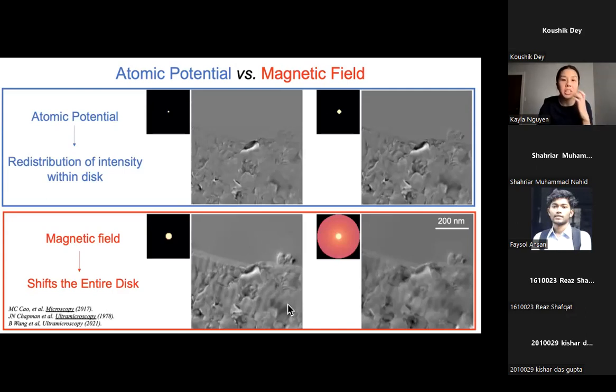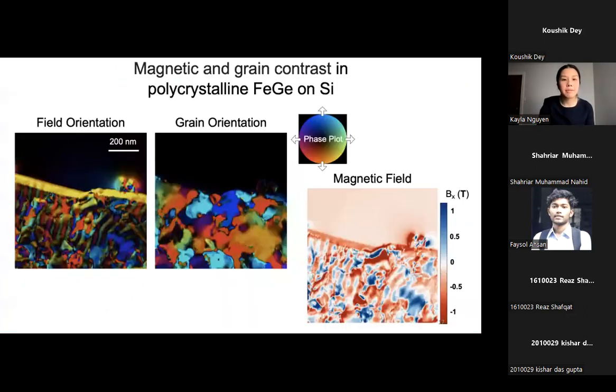So now there's two ways to look at our image. One way is to look at just the grain structure, and the other way is to look at the magnetic shifts. Now that we have two separate ways to look at magnetism and grain contrast, we can separate magnetic and grain contrast in polycrystalline iron germanium on silicon and get back information related to the magnetic fields.